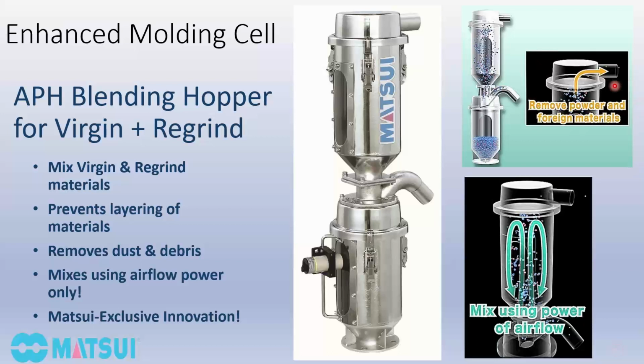So all the dust and fine particles, as the vacuum is being applied, are being pulled through our screen filter back to our cyclone filter, whether it be on our combination dryer loader unit or just on our vacuum loader. So it does a very good job at preventing layering of virgin and regrind material, and also will clean that material right before it enters the injection machine feed screw. A lot of customers who are running clear polycarbonate acrylic parts have been using this with great success to avoid black spot dust contamination.